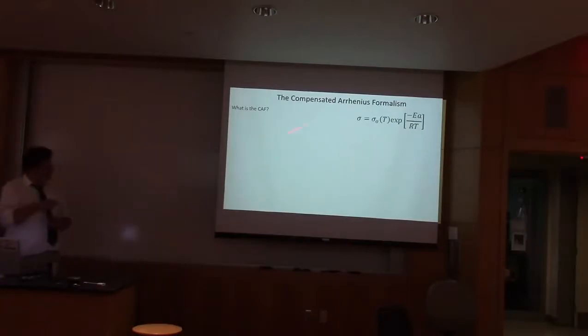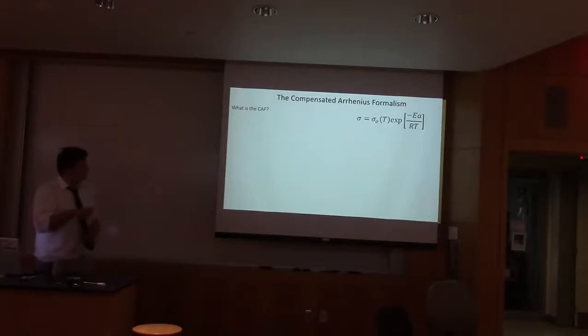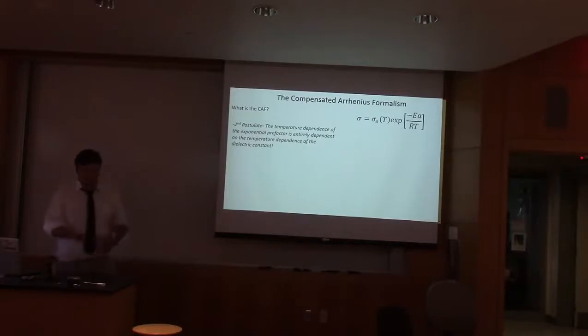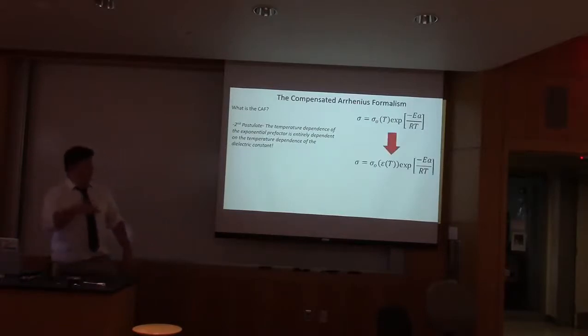Now that we have this general form, we know what makes this in particular a compensated Arrhenius formalism, whereas this is a simple Arrhenius formalism. We suppose, with the second postulate of the CAF, that the temperature dependence of the exponential prefactor, which in this case is the sigma naught, is entirely due to the dielectric constant's temperature dependence. That's a mouthful. That's why I have a little bit that goes down here. So we imagine that the exponential prefactor's temperature dependence is completely due to the dielectric's temperature dependence, just to reiterate.